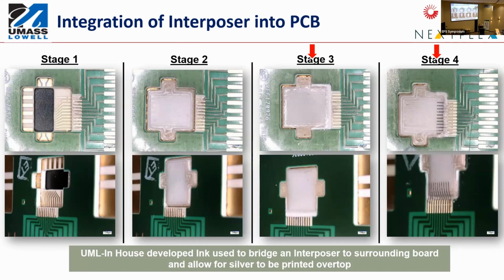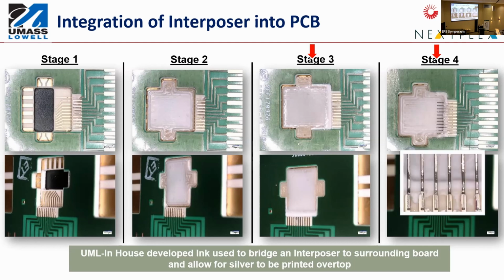Now for that, we actually used our nScript, because we needed to use some other more mechanically robust inks, and those are higher viscosity, so we can't use them in the aerosol jet. Aerosol jet requires less than 1,000 centipoise for the inks. And here's a close-up of what that looks like.